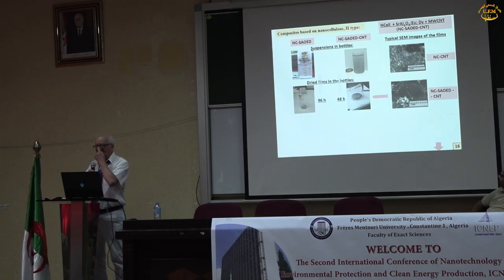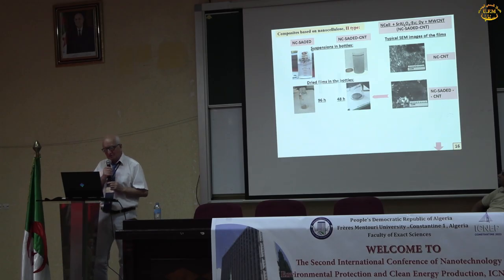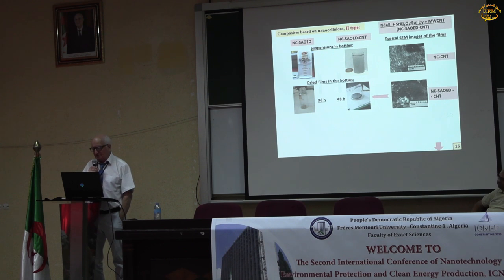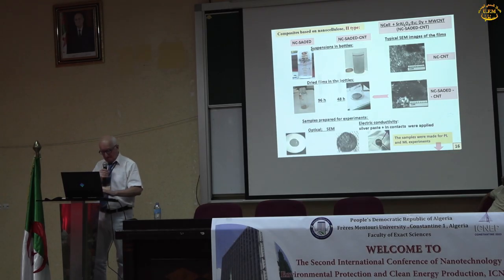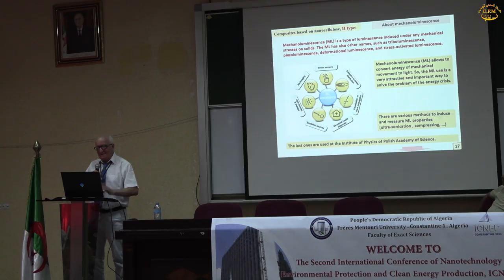We also used some other type of oxide powder in our investigation. This composite includes luminescent powders of aluminate oxide doped with europium and dysprosium ions, so-called strontium aluminate powders. This is the stage of the preparation, the view of these composite materials. The composite materials at the bottom were prepared for electric conductivity measurements. And it is interesting that these materials reveal some other type of luminescence.